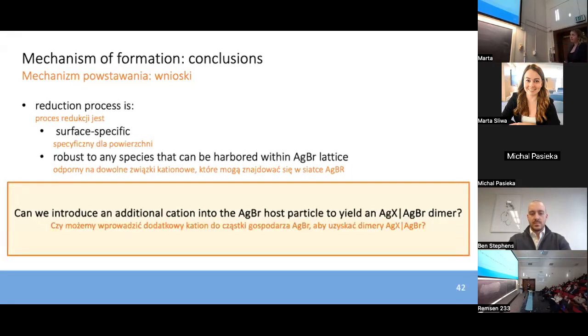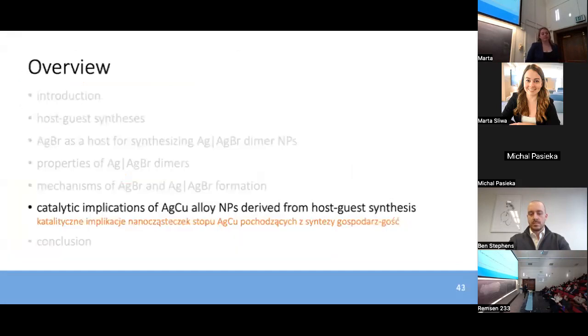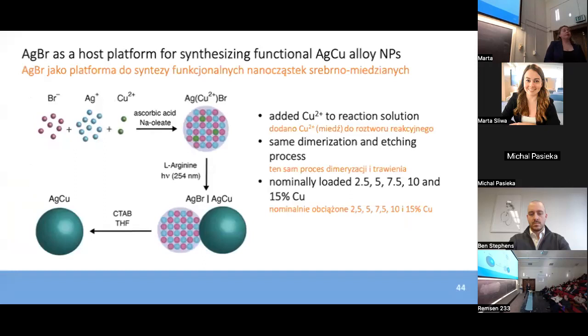So we asked ourselves, can we introduce an additional cation into the silver bromide host particles and eventually yield some silver X silver bromide dimer, where silver X here is an alloy of silver and some prescribed element of our choice. And we tested this hypothesis by using silver bromide host to successfully synthesize silver copper alloy nanoparticles.